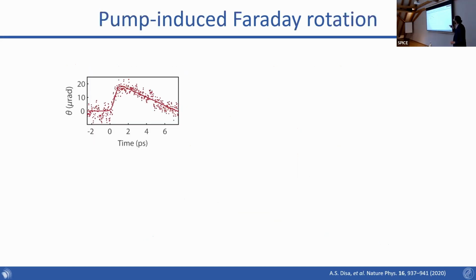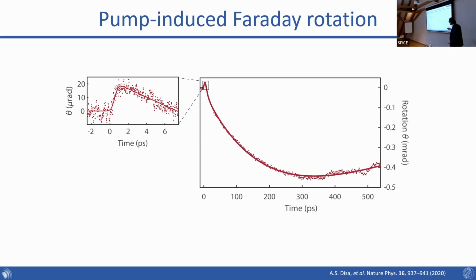And when we do that, this is what we see. So here I'm showing you the trace of the Faraday rotation angle as a function of time. The pump pulse comes here at 0. Before 0, you can see that there's no rotation, as you would expect in this compensated antiferromagnet. And then when the pulse comes, you see this small increase, and then it decays over the time scale of a few picoseconds. So that's interesting, but it's actually not the whole story.